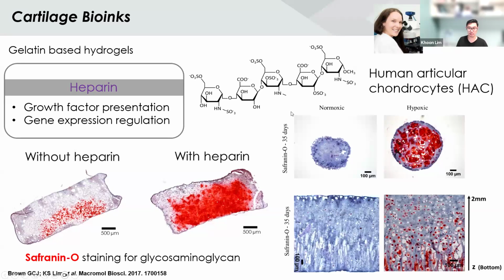So if you do a normoxic culture, for example, you don't see that much tissue. If you put these samples into a hypoxic culture, you will see a lot more matrix production within this hydrogel. And this really does make sense because cartilage in itself is an avascular tissue. So if you now put your chondrocytes into these hydrogels and then put them into a hypoxic culture, you will see a lot more tissue formation. So we thought that was really nice in making a cartilage bioink.